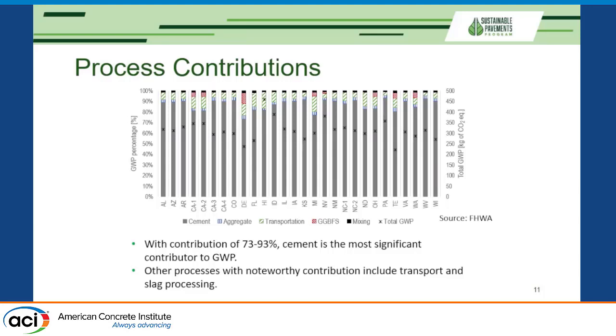This graph here shows process contributions for all of our mixture constituents and processes. So we have cement, aggregate, upstream transportation, slag, because slag needs to be ground before putting into the mix, mixing energy, and these stars here represent total GWP, which is given on secondary axis. So this slide shows us, as you can see, that gray portions of these bar graphs are very, very high, and that means that 73 to 93% contribution of GWP in concrete is because of cement. Other noteworthy processes are also transportation, upstream transport, and slag in some cases. Aggregate is pretty low, mixing typically pretty low.